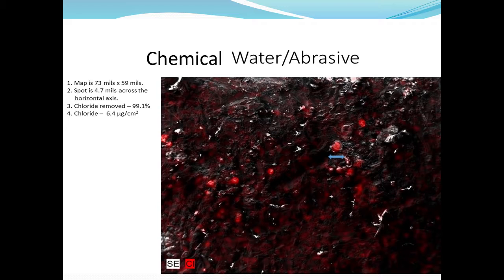And here's why. This is a scanning electron microscope view of a 73 mil by 59 mil piece of one of those panels. After surface preparation, this method yielded 6.4 micrograms per square centimeter of chlorides, 99.1 percent effective. But as you can see here, in doing this scanning electron microscope, an electron beam excites this surface, and it's measuring what elements are coming out, and we told it to color chlorine in red. The experts, which I am certainly not, tell me that a lot of this paler red is like backscatter. If you ran the test long enough, that would go away. But these hot spots are actual